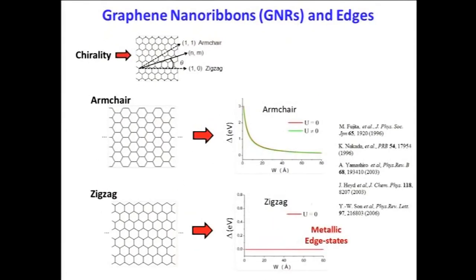If you take graphene and you cut a nanoribbon out of it in this particular direction, then you'll get edges that we call armchair edges. So here's the two sides of the nanoribbon. The nanoribbon extends in this direction. So if you cut an armchair nanoribbon out of graphene, then it's been predicted, and here are some theory papers for various people who have made these predictions, it's been predicted that you will get an energy gap. And that energy gap should behave as 1 over the width.